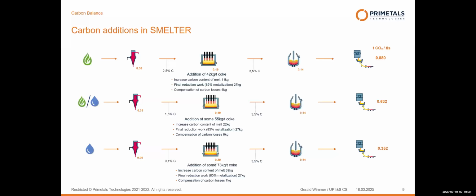What we cannot achieve is saturated, because for saturation in carbon, we would need very long contact of the carbon and the metal. And in this process zone where this carburization takes place, the reaction time or the time where we have contact is limited, so we will not have a hot metal saturated in carbon. So compared to blast furnaces, this is the world where most of us are coming from, and this we know very well. On blast furnace, we have this burden in the furnace where always carbon is present, and the metal therefore is always saturated in carbon. The hot metal from the smelter has slightly lower carbon content than the hot metal coming from blast furnace today.